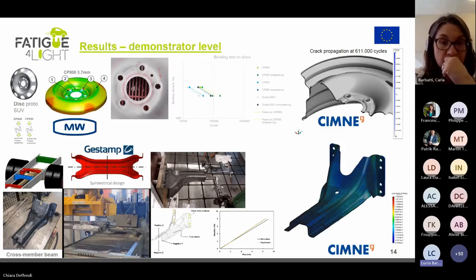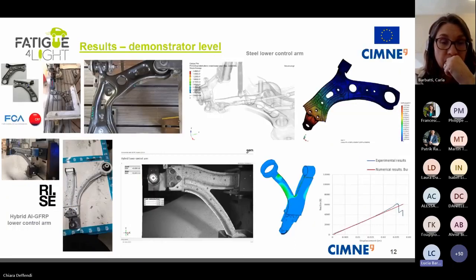but this time we want to model its performance with a hybrid version. So a hybrid version, which means that we have 2 aluminum sheets, 0.8 thickness on the outer parts of the demonstrator. And in the middle, we have a core with glass fiber reinforced polymer, 1.6 millimeter thickness. And this demonstrator was developed at RISE, manufactured and tested at RISE. And ideally, you could have seen here a video of the test.